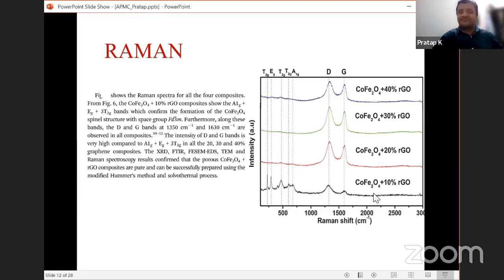The black one is cobalt ferrite with 10% RGO, and red is cobalt ferrite with 20%. Green is cobalt ferrite with 30%. This is cobalt ferrite with 40%. We haven't checked bare cobalt ferrite; we only checked with these 10, 20, and 30. So all these show that there is a graphene concentration here, and the graphene peak kept on improving. It is showing prominently as the concentration is increasing from 10 to 40. So this clearly shows that our composite is graphene with cobalt ferrite.